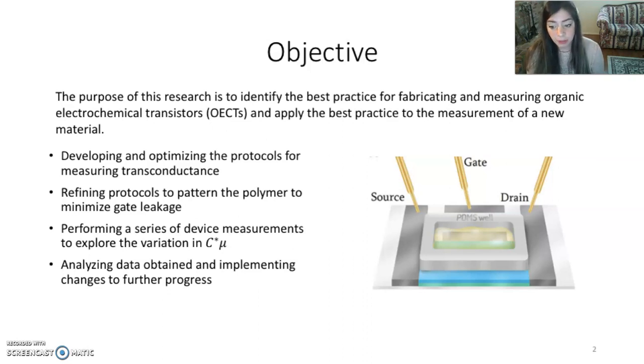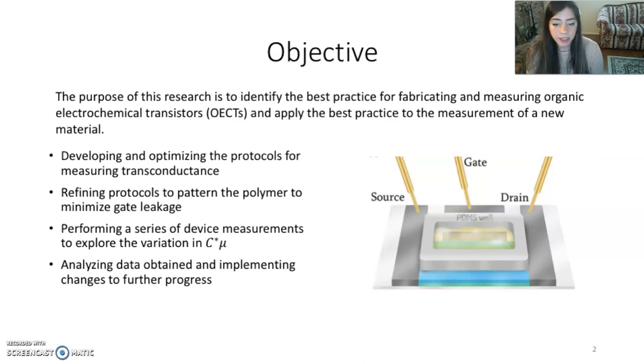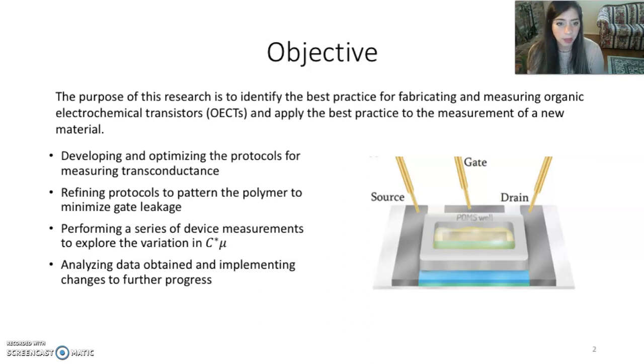This involved developing PDMS wells for holding the electrolyte and gate electrode and then refining protocols to minimize gate leakage. With the best developed practice, experiments were performed to explore the variation in C*μ of a new polymer and explore the performance as a function of film annealing and polymer molecular weight.